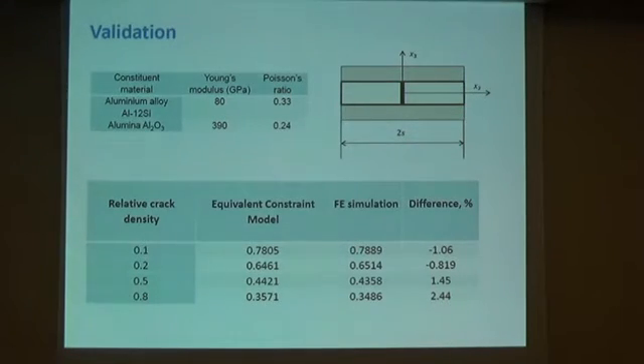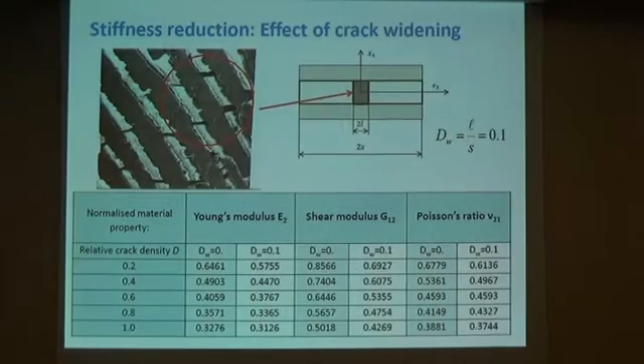To validate the model, we again used our finite element simulation. The results in this table show the reduction ratio for Young's modulus of this composite as a function of relative crack density, which varies from 0.1 to 0.8. This is the reduction ratio for Young's modulus as predicted by the equivalent constraint model, the analytical model, and the finite element simulation. And you can see a good agreement between the two approaches. Say for a relative crack density of 0.1, the reduction ratio is 0.78, meaning that a composite with such density of cracks has lost 22% of its original Young's modulus value. And when crack density increases, that reduction can be quite significant, as the numbers here show.